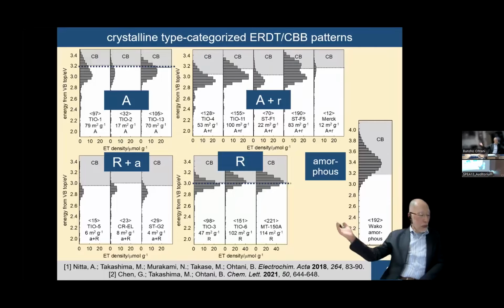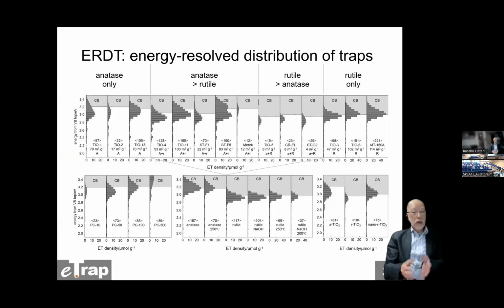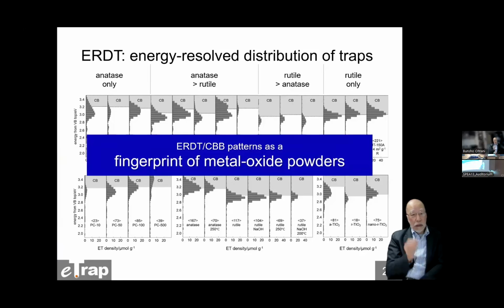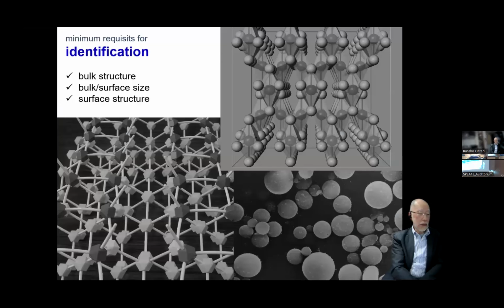For example, among the anatase-only samples, the left top one, TiO1 and TiO13 have almost the same specific surface area. However, the ERDT pattern is completely different. That means they have almost the same particle size, but the surface structure is not the same. So it is possible to say that those patterns can be used as a fingerprint of titanium oxide samples. Even if all these are TiO2, the pattern is completely different. So why can that be our fingerprint?